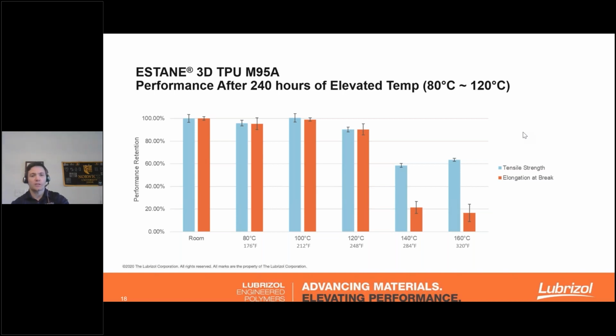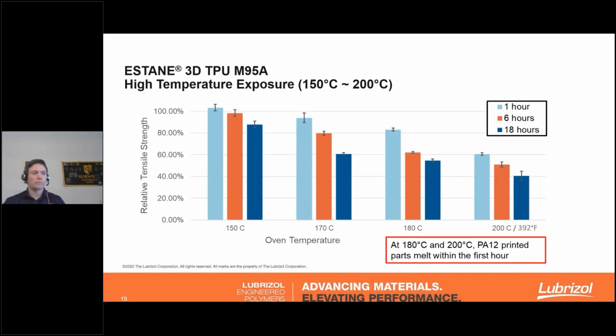We do start to see a loss in properties beyond that point, but this was a 240-hour test, so this is a 10-day test. So we are very happy with the temperature performance of this, especially compared to other TPUs. And we really think that this opens up this material for use in things like the automotive industry for certain applications.